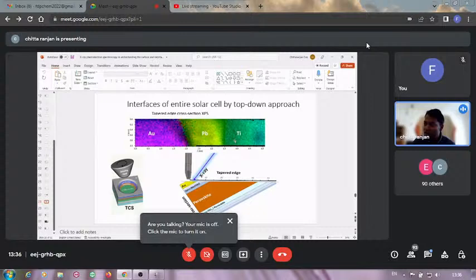And also we did similar things, and probably it's too much information for you. So what you do, we cut a solar cell. The solar cells are a few micrometers, and we cut it and we measure in different positions. And depending on the position, here you can see it's gold, and the green area is lead, and the carbon is mostly present everywhere. And carbon is one of the contaminations. It's present everywhere, so you cannot get rid of it if you don't prepare your samples inside the glovebox.